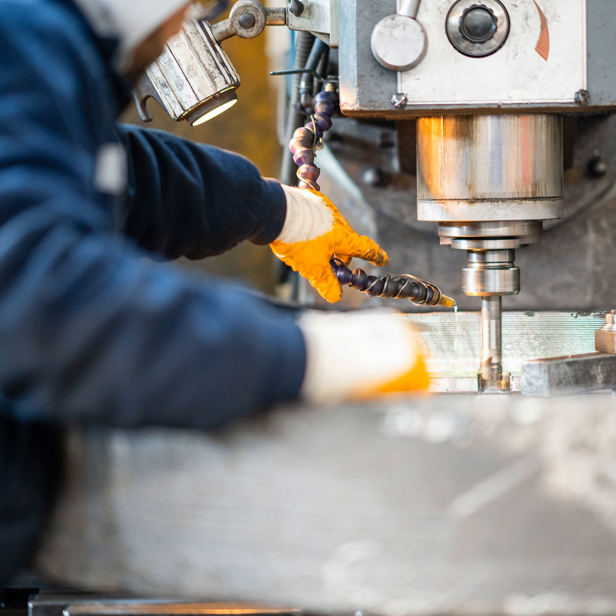So when we do a deep dive into the geometry, we have applied an asymmetrical flute configuration coupled with an irregular pitch with the flute spacing. What this gives is more stability throughout the part. All the cutting angles are attacking the workpiece at different angles. There is no commonly shared helix angle. This creates added stability to the cutter, reducing harmonics. We have furthermore optimized the cutting relief angles, engineered for ISO-S materials such as titanium alloy and nickel-based alloys.